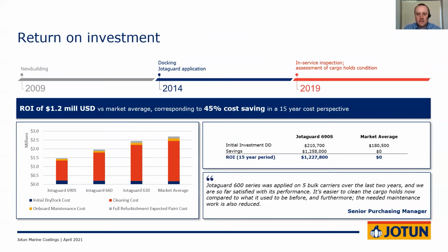So in summary, and to put some dollars and cents to this, here we can show that for a very small initial coating investment, which is shown here on the right-hand side of the slide, approximately $30,000 addition from 210,000 versus 180,000 for the refurbishment of a Handymax bulk carrier, you can have a 7-figure return of investment, or roughly a 45% saving on your cargo hold cleaning and operations and coating, taking into account the cost of the coating itself, the cleaning that you'll do throughout the operational period, the repairs that might be necessary, and the major refurbishments.